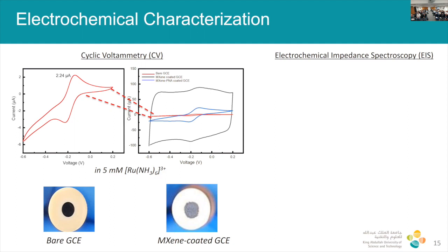There are very high electronic conductivity properties of MXene, enabling electron transport through it. Now, in blue, what you see here is if the MXene was PNA functionalized. So we have PNA functionalized MXene also deposited on the surface, and of course you get a reduction in current because now our MXene surface is actually covered with PNAs that are hindering this electron transport and hindering this redox reaction, which is what we expect as proof that it's definitely something functionalizing the surface, and we know from the previous results that it's definitely PNA.